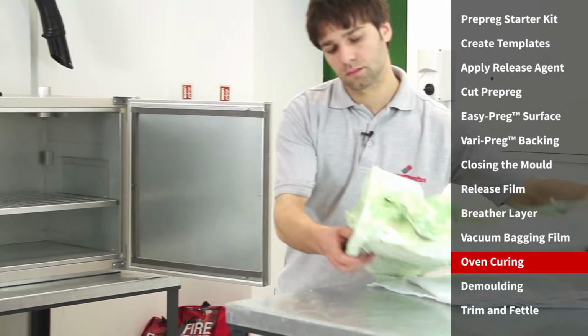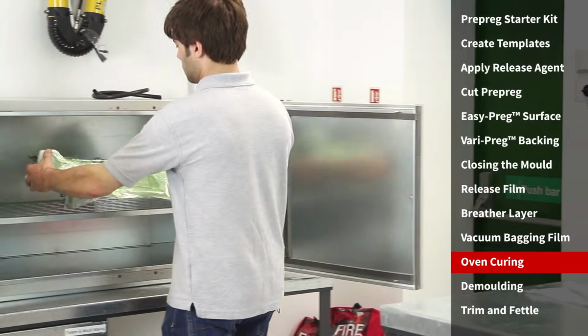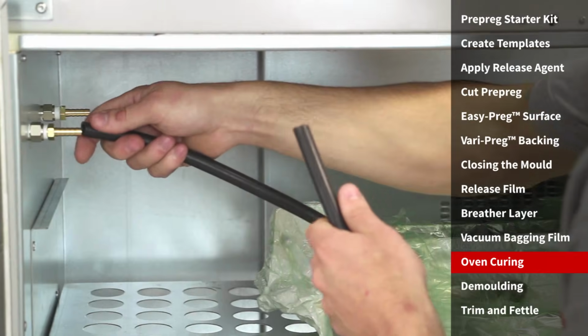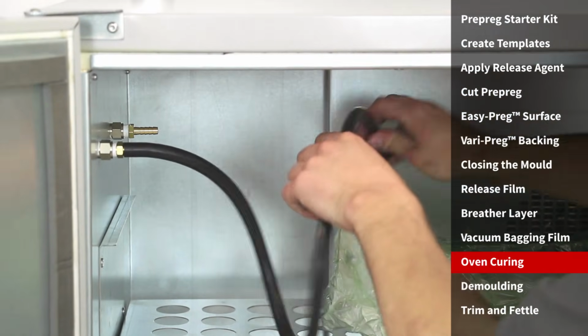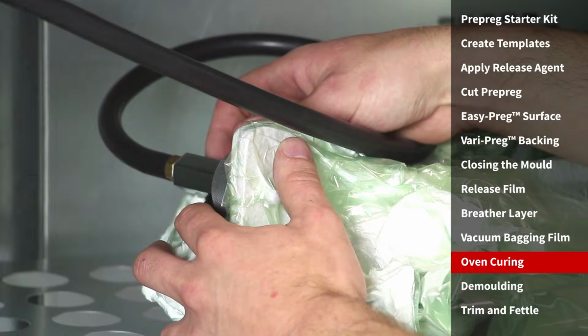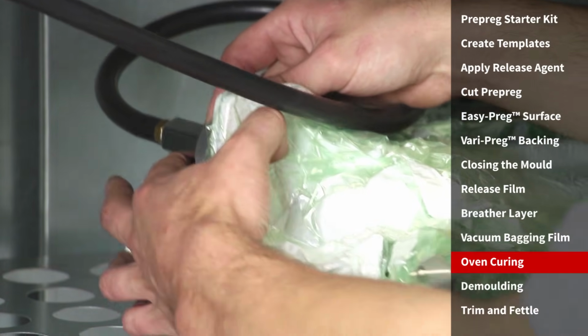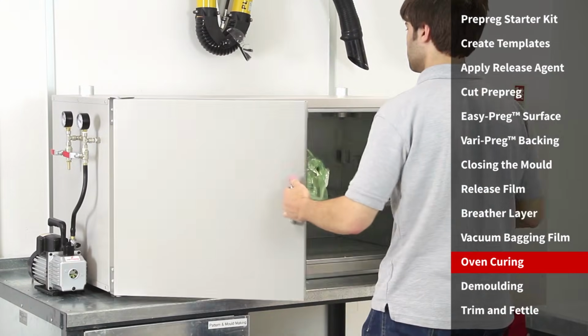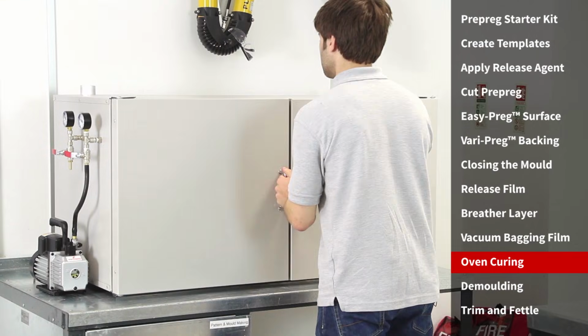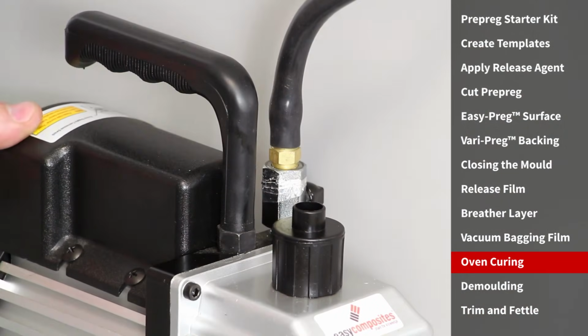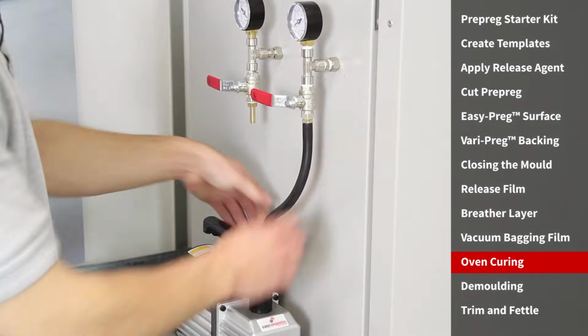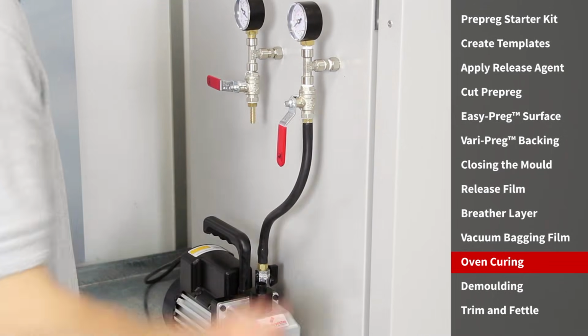Here we're using our own specialist Composites curing oven, which gives us plenty of space for loading parts like this, and also has vacuum lines already available inside the oven. It is, however, perfectly possible to cure pre-pregs in a range of different types of oven, from small domestic ovens through to large industrial ones. The key thing is that you need a vacuum line into the oven to maintain vacuum throughout the cure.